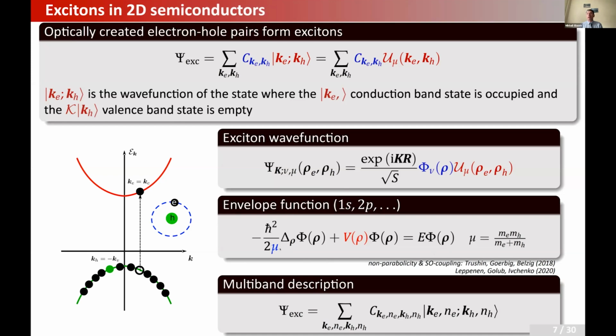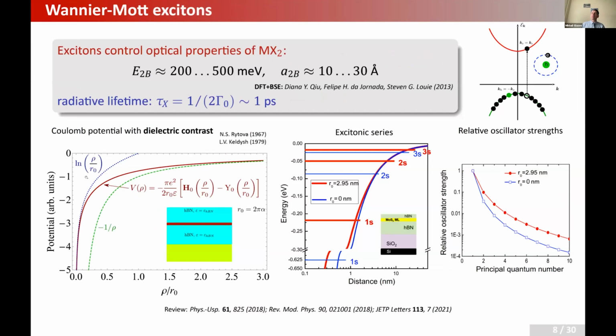For transition metal dichalcogenides, this mu is about a quarter of the free electron mass, so somewhat lighter than the free electron. And V is the interaction potential. In transition metal dichalcogenide based systems, this potential can differ from simple Coulomb interaction for the following reason. Typically, the structures people study consist of a two-dimensional semiconductor encapsulated, say, in hexagonal boron nitride. If electron and hole are relatively far apart, then of course the electric field permeates the surroundings, and what we have is just the Coulomb potential at large distances, screened by the environmental dielectric constant.